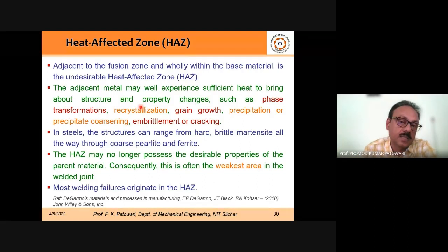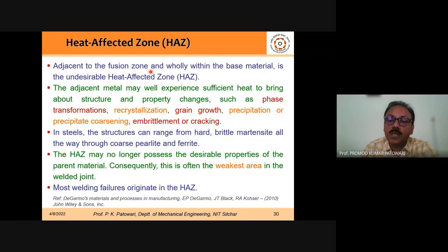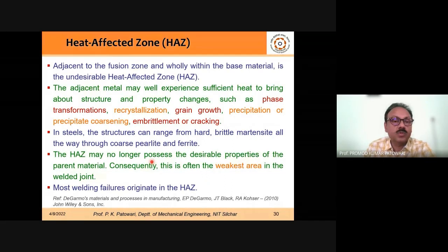Now, what is this heat affected zone? This is basically adjacent to the fusion zone area. It is within the base material, and that is very much undesirable. This adjacent metal will experience sufficient heat to bring about structure and property changes, because of phase transformation, recrystallization, grain growth, precipitation or precipitate coarsening, embrittlement, or cracking. So many things may happen, and because of that, we are getting a different material than the parent material. Most of the failure occurs in the heat affected zone, and that is the weakest area.